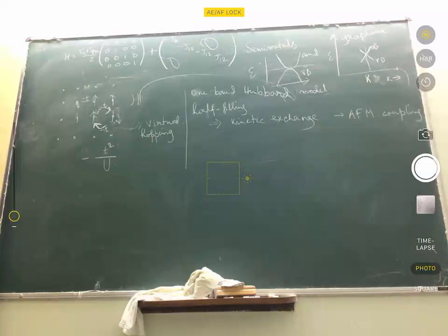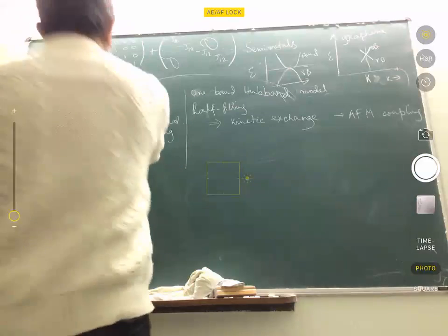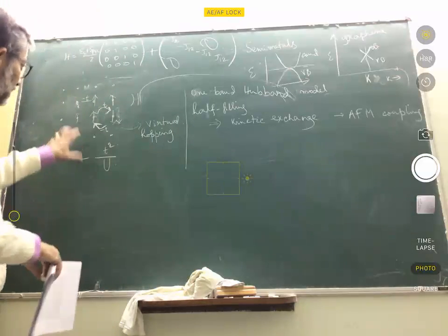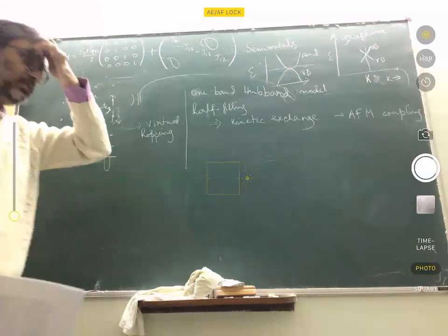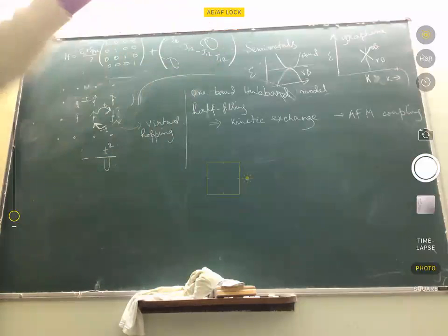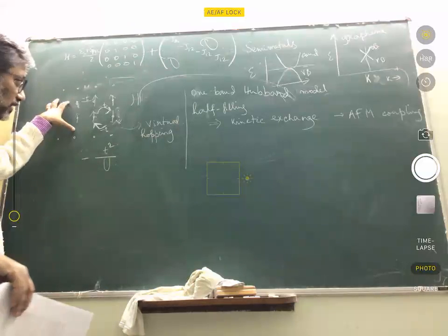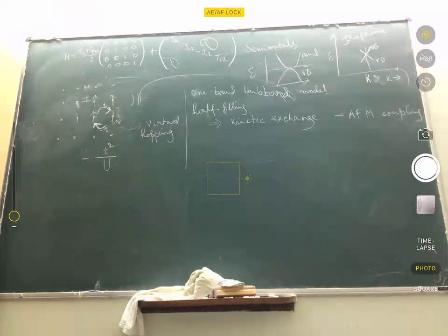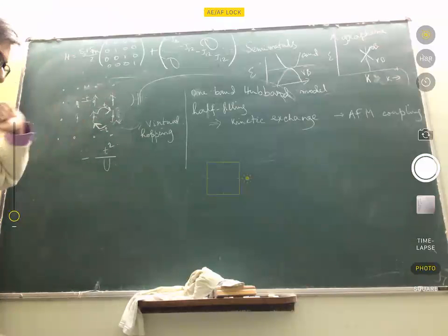Okay, so this justifies a Heisenberg kind of model. Electron propagations where I really have to worry about states at energy U relative to this ground state are completely discounted because U is large enough, but such virtual hopping processes are allowed that give rise to an antiferromagnetic coupling between the spins on neighboring sites.